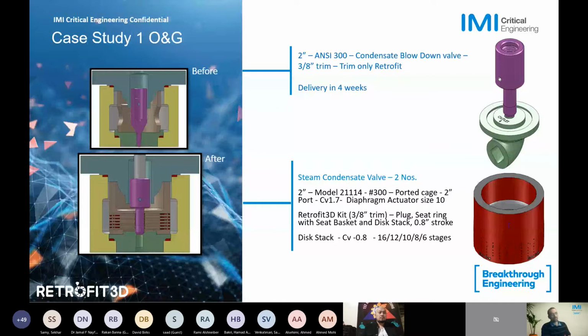And so we approached this issue with a twofold solution. The first one was, this was a flanged valve, so we were able to change the flow direction from under the plug flow to over the plug flow so that the bonnet is no longer negatively impacted. And then to protect the valve body from this flashing service, we included a flow diverter here. We call that a seat basket on the bottom. So when you imagine you have your flow going through the seat here, it's being diverted away from the valve body with a 90-degree elbow here, that is forcing the medium to go towards the outlet of the valve.